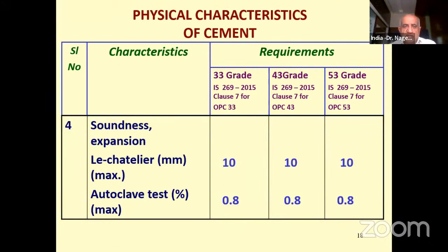Another test we normally do is the soundness test. Soundness test gives the presence of free lime or magnesium oxide. Free lime is determined through Le Chatelier's test, and autoclave test gives the presence of MgO in it. So these are the requirements. 10 mm maximum is allowed for Le Chatelier's test, and for autoclave test it is 0.8% maximum. This is the expansion which is allowed.